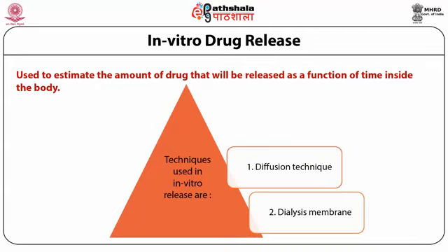Drug should not be absorbed by the dialysis membrane, and the membrane should be freely permeable to the active ingredient. That is, the cutoff molecular weight of the dialysis membrane should not hinder the process of diffusion. The first step of the procedure of this technique involves putting a small amount, a few milliliters, of the liposomal suspension in the dialysis bag, which is hermetically tied.